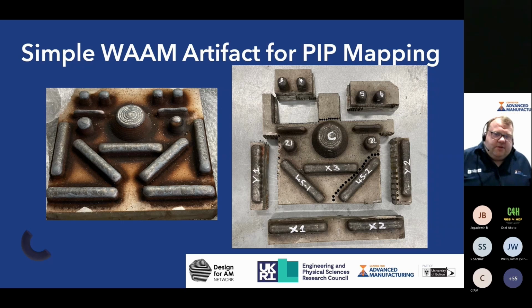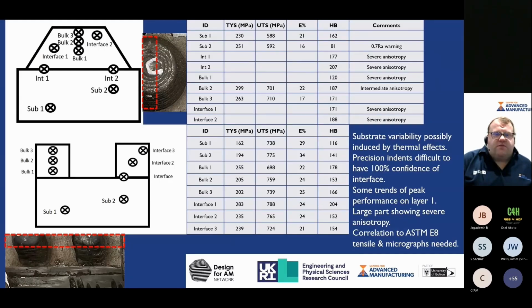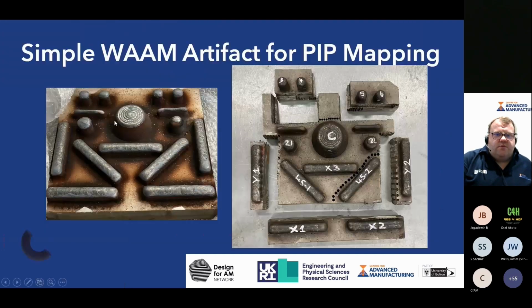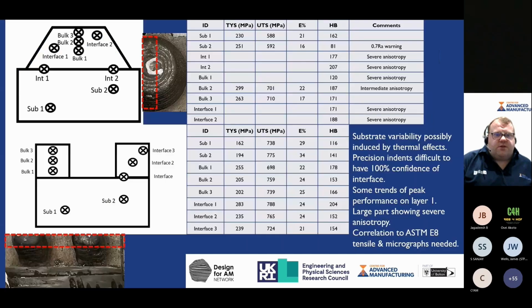Unfortunately, the build had to be stopped relatively early, so we didn't get the Z height that we needed to be able to do the ASTM-E8 type coupons. But in the interest of making sure that we had data ready for today, we went on and did a PIP overview, focusing on the cone and this section at the top. These were meant to be cylindrical Z height tensile coupons.